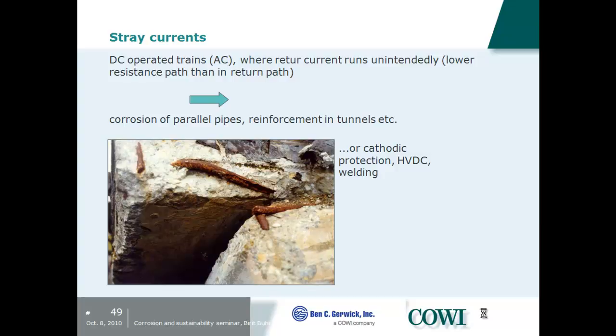This picture is a picture I took of segments in the Bucharest metro at least 12 years ago. They were making a new station, and they took out the old elements, and so it was an element churchyard they went to. They were heavily corroded, and I thought there must be chlorides in this because it was pitting corrosion. I took some concrete samples home with me. No chlorides, and it matched very well with that. They had rivers through the alignment and so on, but no chlorides there. We did measurements, and it was stray currents and stray current corrosion.